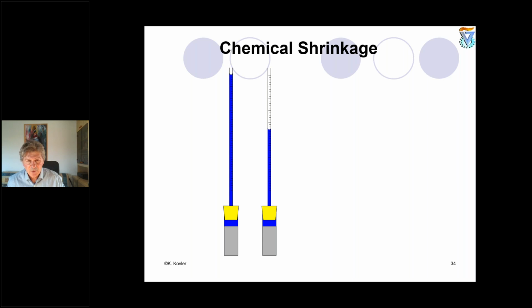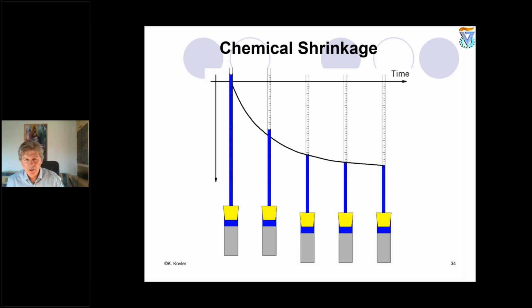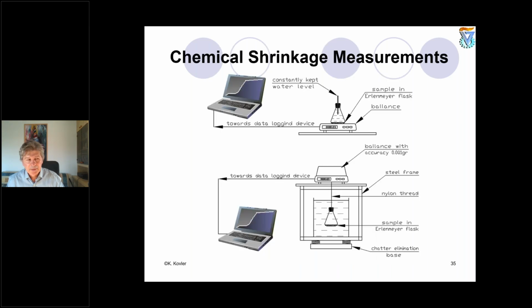It doesn't evaporate, because these conditions were not characteristic for evaporation. So water didn't disappear, but what happened? Where did the water go? He understood the water filled the internal pores forming in the system. And so chemical shrinkage is a reduction of volume, an internal volume reduction. It is very difficult to see it from outside.